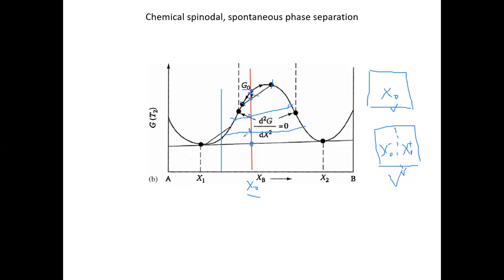So if you further move forward, you're gonna have an increase again. Well, this means that everything is consistent, right? If I'm in this dome, I know that the system wants to be in the two-phase coexistence regime, and if I start the transformation process by having small fluctuations of x minus and x plus, I see that I have an immediate decrease of the free energy. And this free energy reduction is enhanced as the separation proceeds.